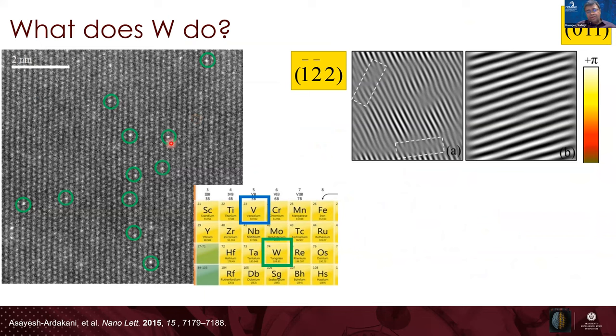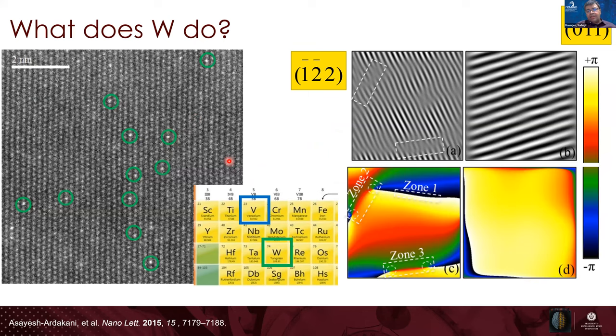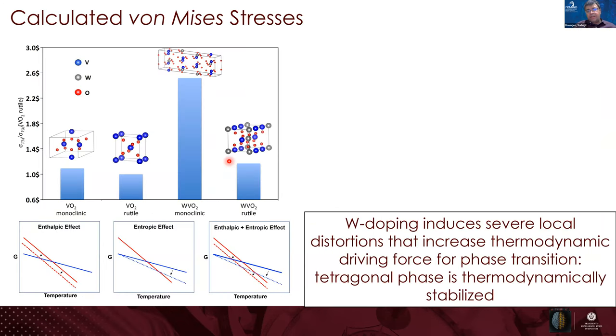And so what does the dopant do? This is a tungsten, with Reza Shahbazian-Yassar's group at UIC. And essentially tungsten applies this massive anisotropic strain in the lattice, and these large dopants, because of the strain, the monoclinic phase ends up getting quite distorted, right? And this large distortion therefore increases the thermodynamic driving force of the phase transition. So you end up stabilizing the tetragonal phase at a lower temperature.